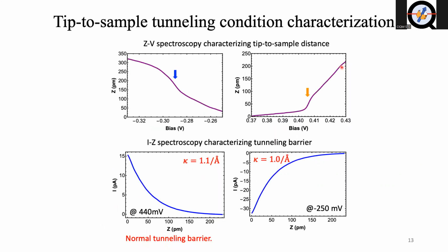Okay, so a little bit of technical spectra that is specifically for STM people in my group. As I said, maybe I did not convince you that the tip to sample distance may change, but here we did the Z-V spectroscopy characterization of tip to sample distance. You can see that there is a discontinuity at this bias, and that signifies the tip to sample distance is increased at this bias because the tunneling current was kept constant, and that is a signature of a reduced amount of density of states when it goes past this threshold energy.